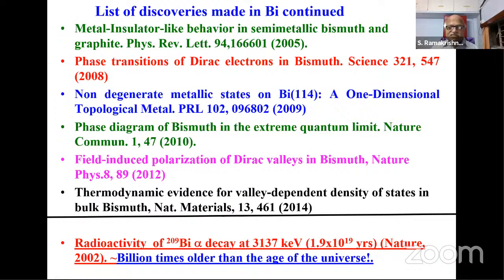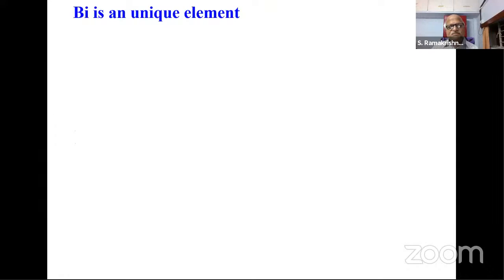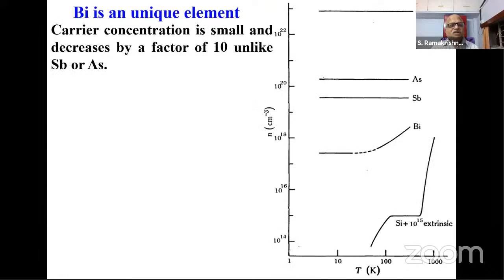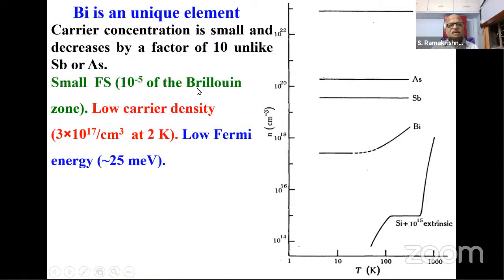So you can safely say that bismuth is stable and then move away from that point of view. But it's an interesting twist which came several years ago. So what is again special about bismuth? I told you that unlike the other metals, where the carrier concentration is flat, there is no temperature dependence of the carrier concentration. Bismuth is really funny. It still has a temperature dependence of carrier concentration. As you go from room temperature to the low temperature, it goes down by a factor of almost 10.